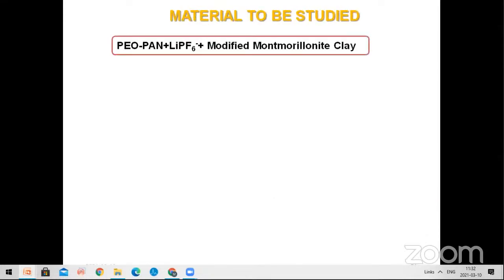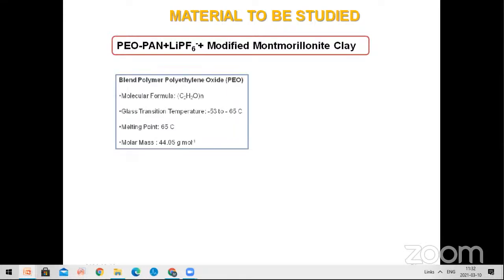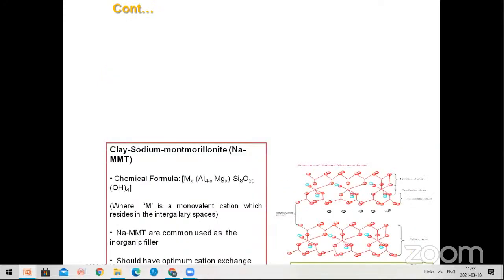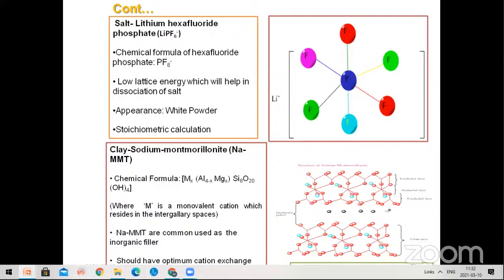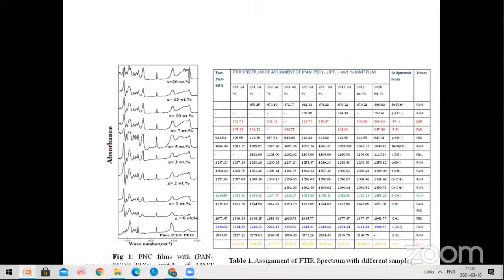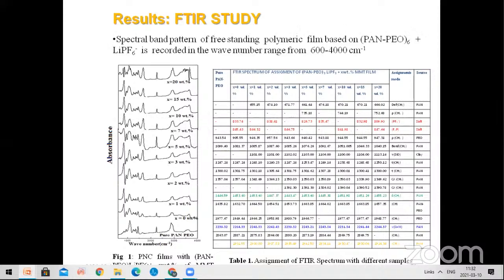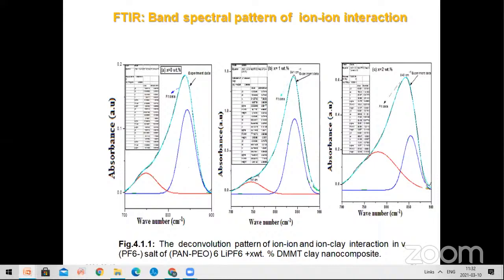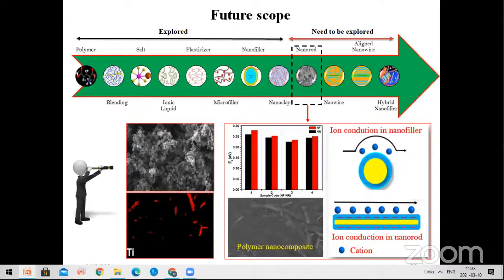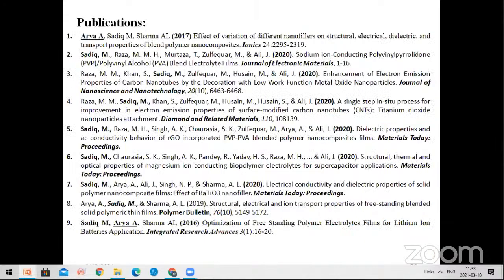In another study, we take PEO as a host polymer, and we take LiPF6 as a lithium salt and different concentrations of the DMMT modified clay. These are some structures of the modified clay as well as the lithium salt. In this case, again, we take the FTIR analysis for the various band information, and also we deconvolute these patterns to find out the free ions and cation ratio. And these are some applications and these are the publications.